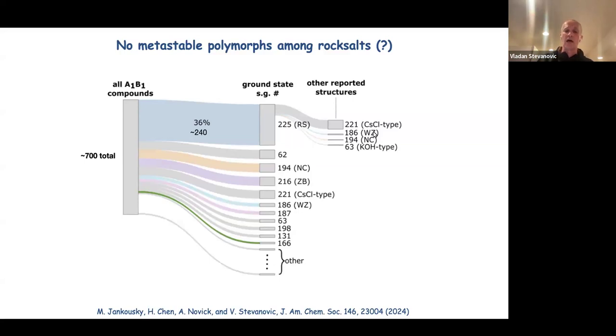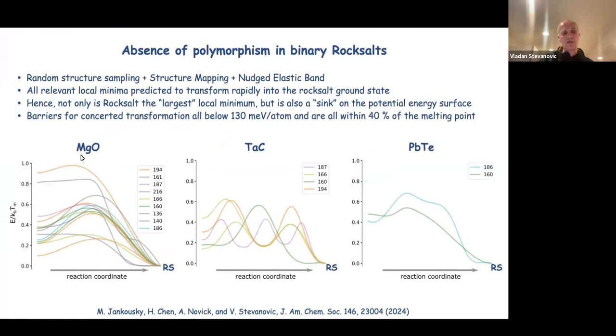So then we said, can we apply both our random structure sampling to identify which local minima are statistically more relevant, hence more realizable, and can we then apply our mapping algorithm with periodic boundary conditions, like the one that I showed you a moment ago, to identify whether there are local minima that could potentially be long-lived? We studied 3 systems: magnesium oxide, tantalum carbide, and lead telluride. We took all the statistically relevant local minima that we found, applied the mapping algorithm, and then did this barrier estimation, or the bulk barrier estimation.